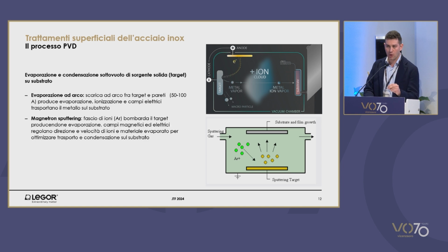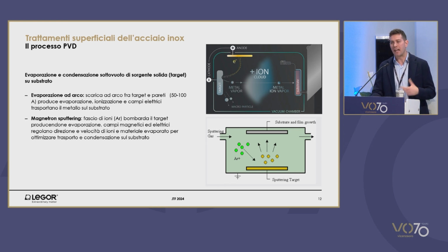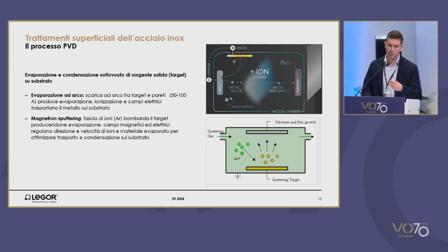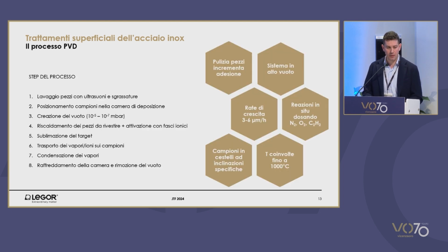A high-energy ion beam bombards the target, detaching atoms or molecules that move into the chamber and condense on the substrate. Both technologies include the transport and recondensation of the vapors emitted by the target. Nowadays, technologies include high energy ions that produce vaporization. This is called, again, ion plating technology, that allows for the transportation of vapor so as to make the development of the coating as homogeneous as possible. PVD includes a pre-treatment of the sample.